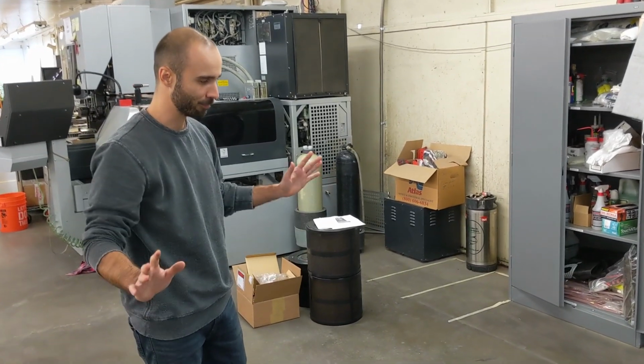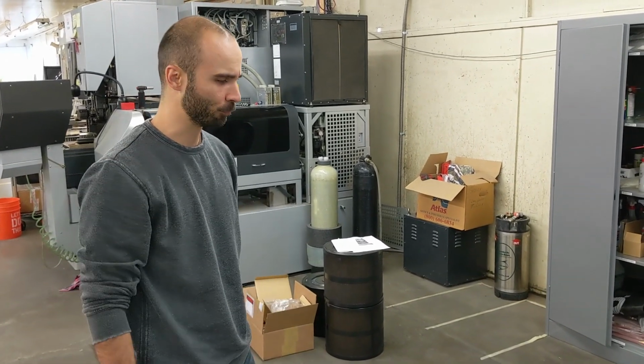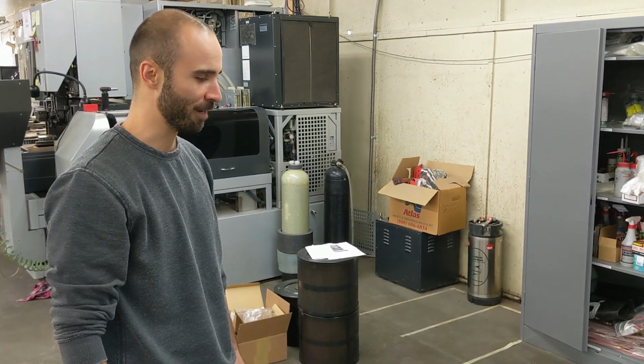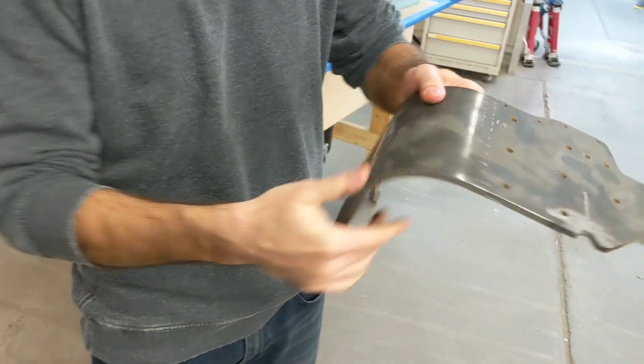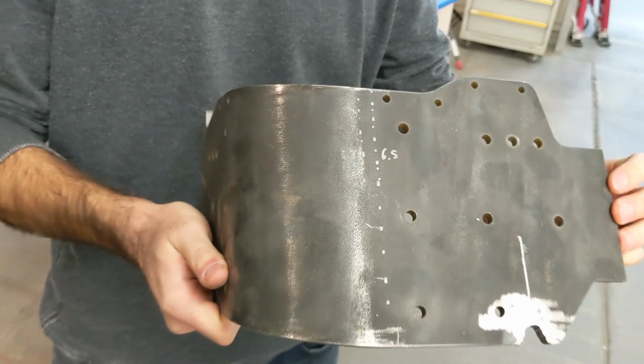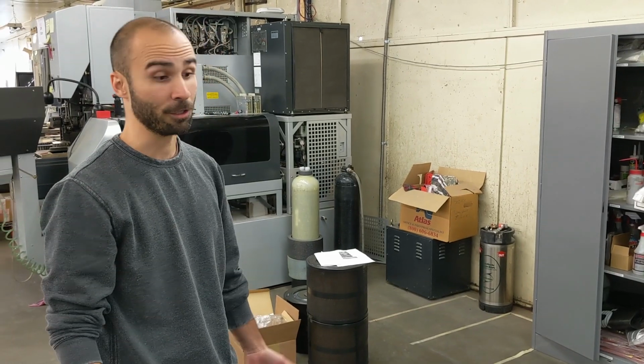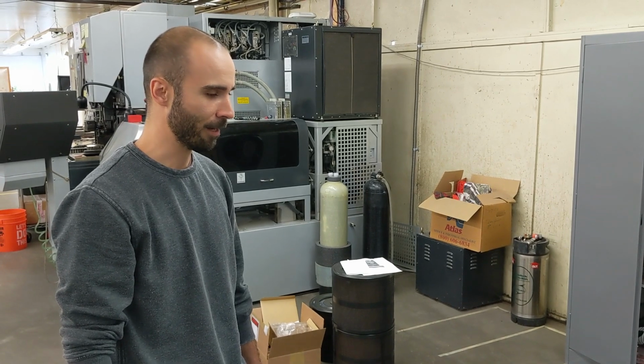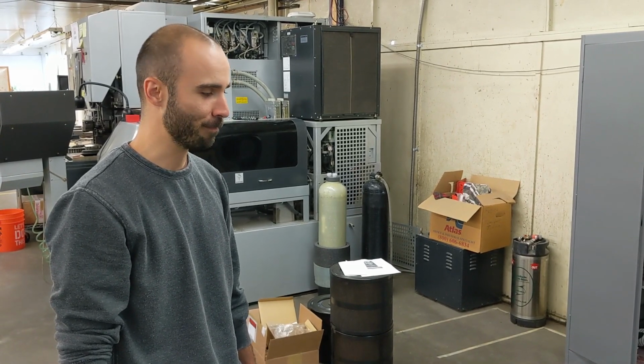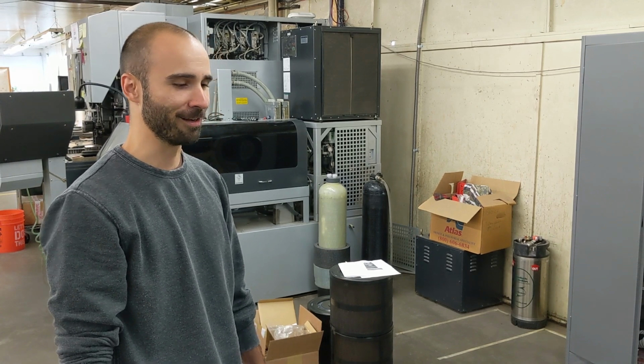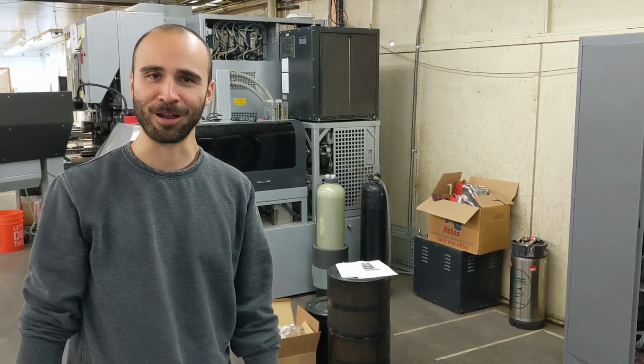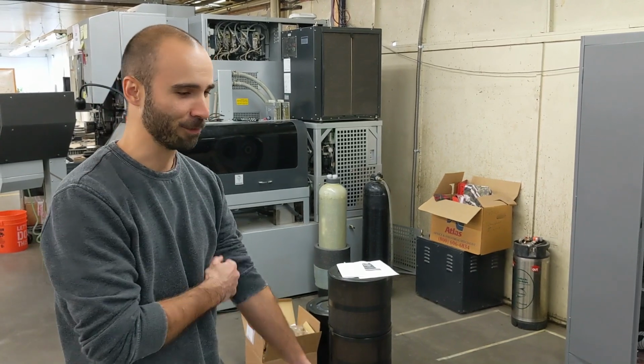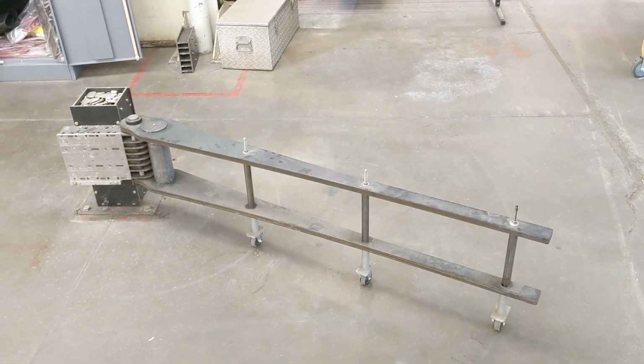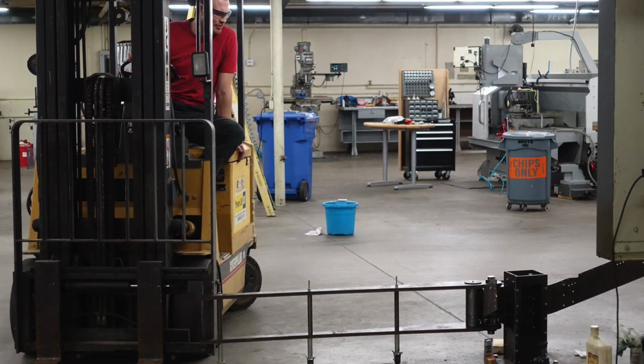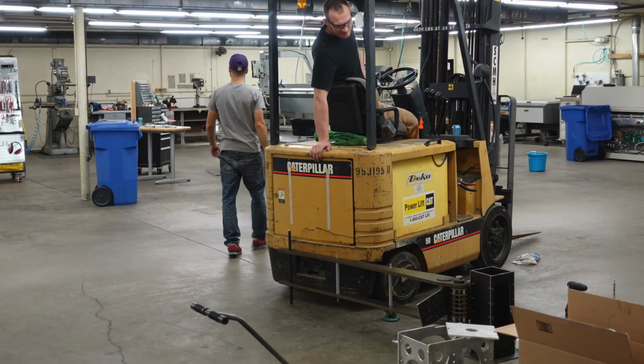The art of bending is a super magical thing, which we don't really understand. We took our best time of calculating all different parts associated with it, such as the bend radius, the material thickness, bend start point, etc. And we got pretty close, but we unfortunately drastically underestimated how much force was required to bend AR-500. And so this was our best guess here, which is a 5-foot lever arm. But in reality, we actually need a forklift to move it, which is very humbling.